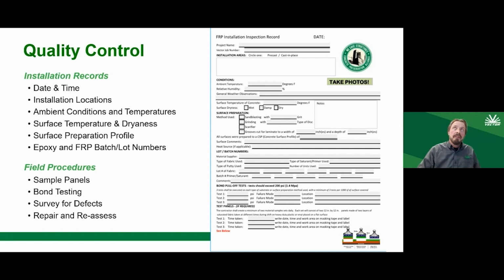We don't want high relative humidities or dew points where we're having condensation of water on the concrete. You might see that in a coastal area or something like that. Surface temperature, and then making sure that it's not wet or damp. We do use a moisture testing meter where we can set it onto the surface of the concrete and it'll tell us the percentage of the moisture on that concrete. Typically we want the moisture below 3% prior to installation of a carbon fiber fabric.